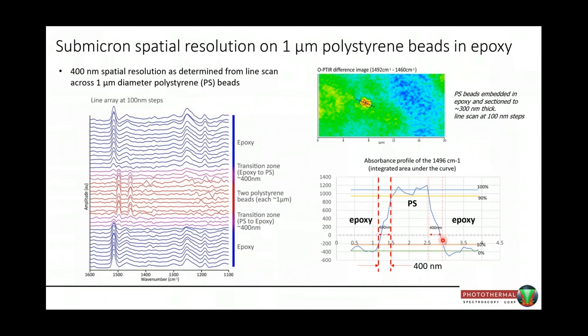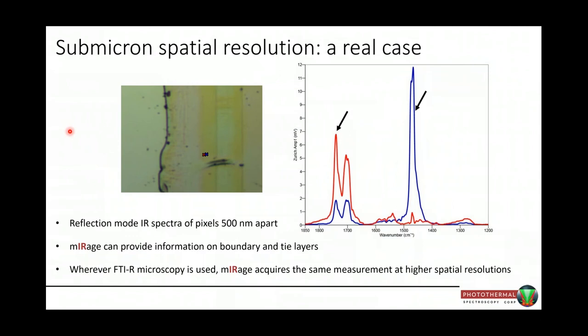This is a real sample of multi-layer packaging film for food, where we show two spectra that were collected 500 nanometers apart in different layers, and you can see a clear transition between this ethylene vinyl acetate copolymer and more of a polyethylene layer just within a 500 nanometer step. That means you can sometimes detect these important thin layers that are in multi-layer film samples.